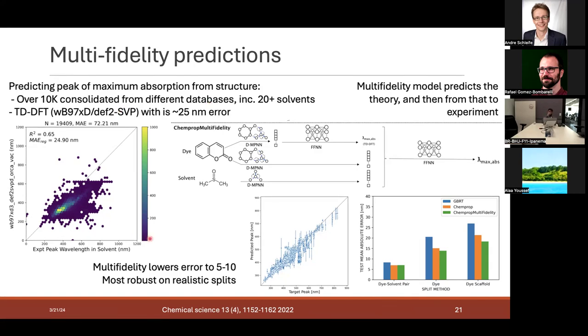So in this example, we tried to do the best of both worlds, right? We have a theory that works, right? It's not amazing, but does some work. And we have a lot of experimental data. So we took one of these graph neural networks, but we twisted it into what we call a multi-fidelity model to be able to exploit thousands and tens of thousands of simulations and thousands or tens of thousands of experimental data points. So what we did for this one is that we trained the machine learning model to predict first what theory would say.